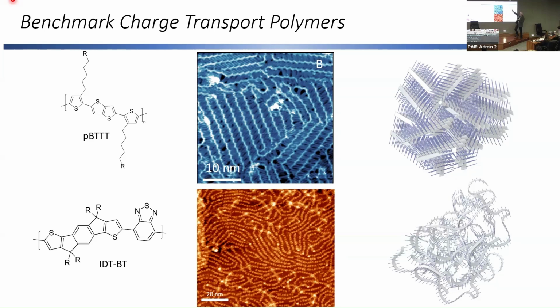Whereas the motif for PBTTT is of like sandwiches coming together. You've got this pi-pi stack, very strong pi-pi stack, and a lot of linear stacking. Transport is very fast within these lamella, but when you go to the boundaries, it's not always so good. Whereas in the case of IDTBT, there's these opportunities for very fast intramolecular transport and aided intermolecularly by these short contacts. I'll talk about this a little bit later.